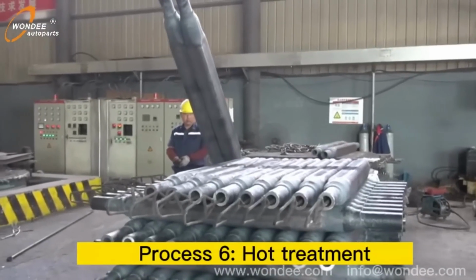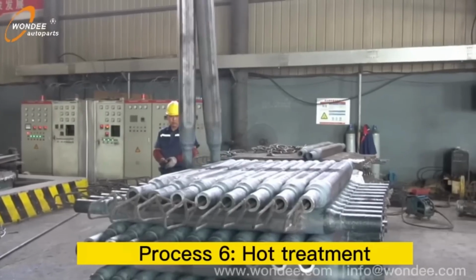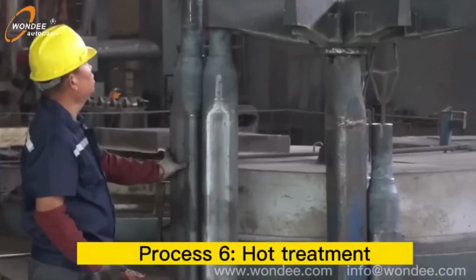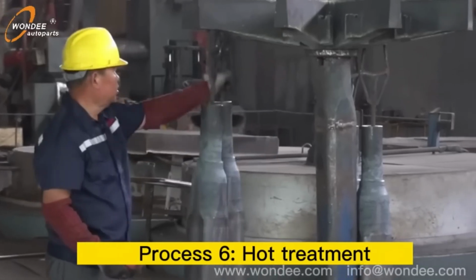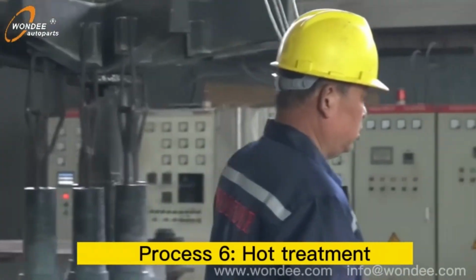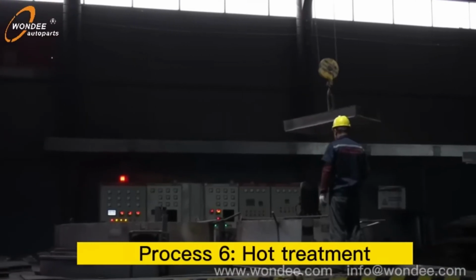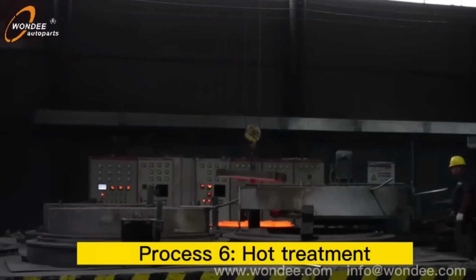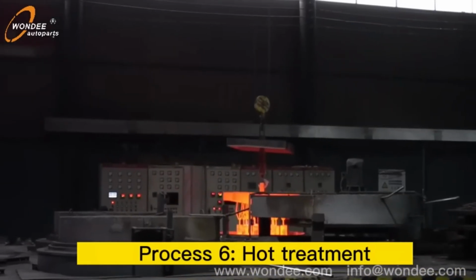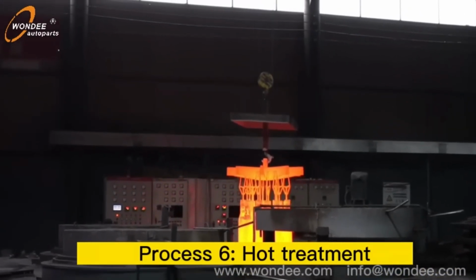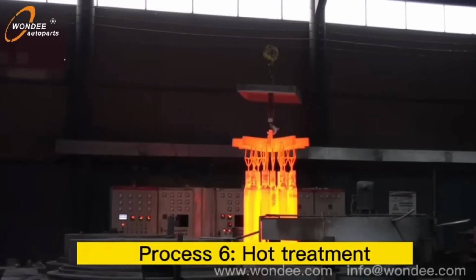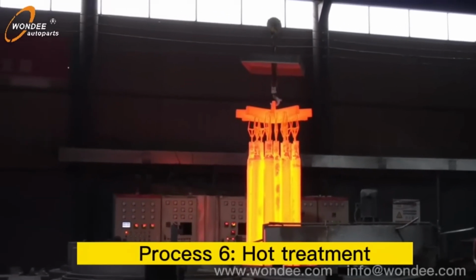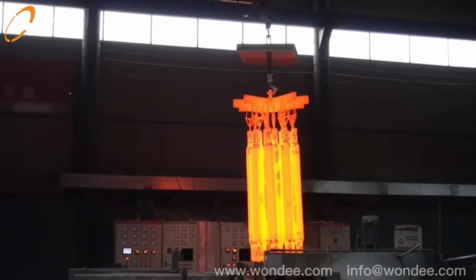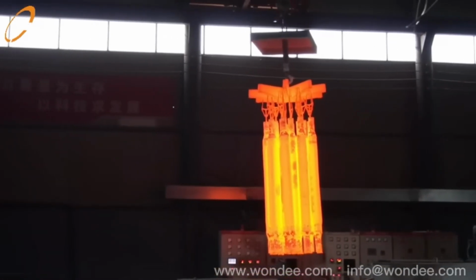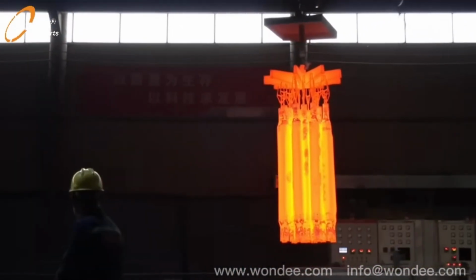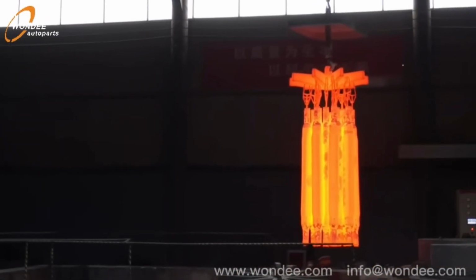Heat treatment, also called hot treatment, is a crucial step that improves the axle's mechanical properties, durability, and performance. During this process, axle beams are heated in large furnaces to temperatures typically ranging from 850 degrees Celsius to 950 degrees Celsius, depending on the steel grade and desired properties. The heating stage relieves internal stresses from previous forming operations and refines the steel's grain structure. Once at the target temperature, the axles undergo controlled cooling, either rapid quenching in oil, water, or air, or slower cooling for processes like normalizing or annealing.